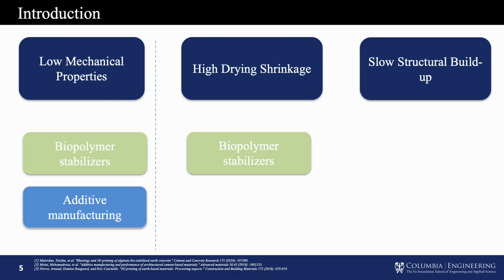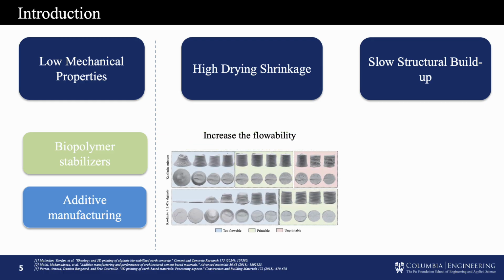Then the high drying shrinkage. How can biopolymers mitigate the high drying shrinkage of the material? We can see that some biopolymers, like sodium alginate, which I'm going to introduce today, can work as a superplasticizer. Therefore, it can enable smooth and continuous printing of the material with a high solid volume fraction, which has less water. Eventually, it will have a lower drying shrinkage rate.